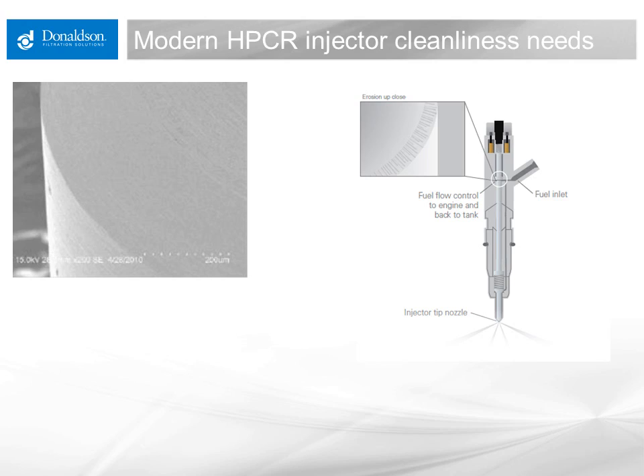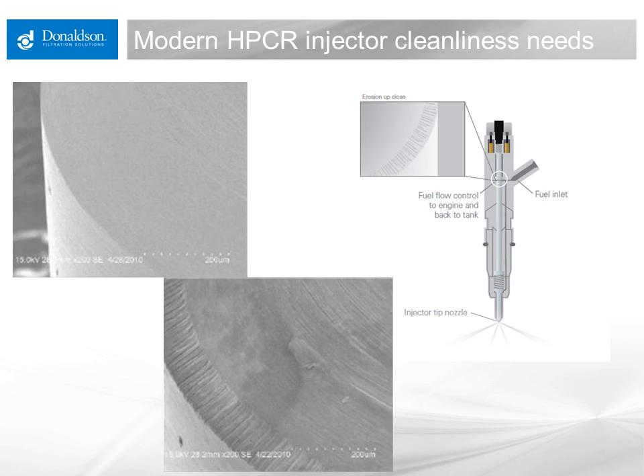That scanning electron microscope image is an undamaged surface. That valve is opening and closing three to five times each time the piston comes up in the cylinder and controls injection flow of fuel into the cylinder and away from the injector. If that surface in that valve, which has a maximum open tolerance of about three microns, has particulate trapped in it when it tends to close, it can impact the surface between the two mating surfaces of the valve, beginning to dimple the surface and then shortly thereafter getting fuel to flow across that surface and begin to leak. That leakage of high pressure fuel at 30,000 to 45,000 PSI with fine particulate in it will cause erosive wear across that surface and begin to allow additional leakage back to the fuel tank and decrease the control of fuel being injected into the cylinder. The engine will then not meet emissions requirements, it will produce additional soot, and you'll be getting downtime and having to do injector repair.